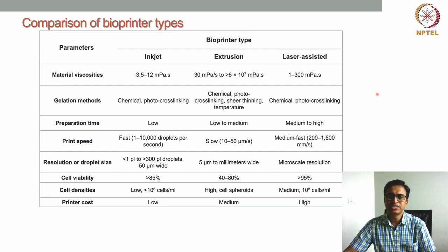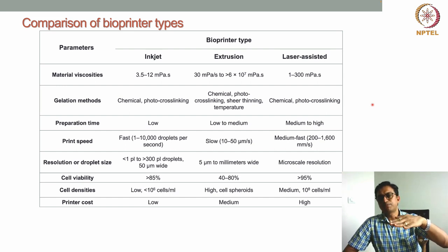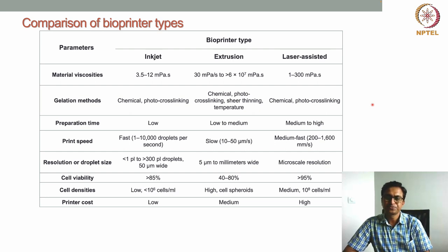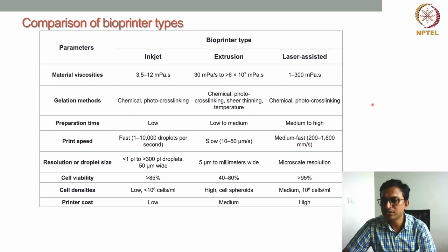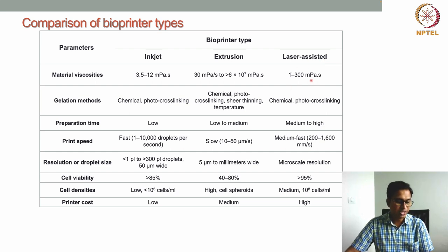In case of laser-assisted bioprinting, low to moderate viscous materials are used; very high viscous materials cannot be used. If you recall the mechanism, there is a ribbon-like structure with a glass layer on top, then an energy-absorbing metal layer where the laser strikes. The metal layer heats up, producing a bubble due to high-pressure gas that propels the droplets. Using very high viscous material would cause a problem in droplet generation.